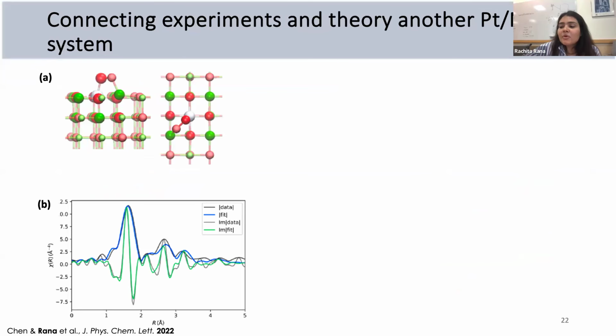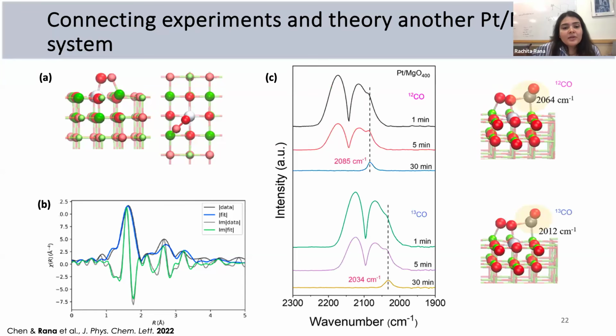This is another example of a platinum and magnesium system where we had a completely different site. This was a surface site of platinum, and we used QuantEXAFS to get the structure. Based on that, because we had a specific structure that we could utilize, we could compare the infrared absorption CO DRIFTS experimental results, what you see here, to computationally calculated vibrational frequencies, and they were in agreement with the experimental results.